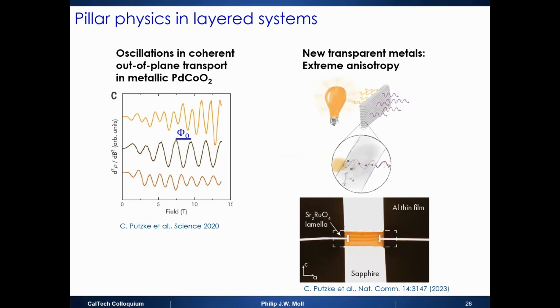These are layered materials. They like to go in the AB plane. Everybody knows how graphite looks. It's that black and shiny. And they like to grow in these big plates. But if you somehow take a slice, like you cut a slice through this, so you make an AC plane, you have a very interesting structure, because now this is highly conductive in the sheets, but is highly insulating, or at least very poorly conductive in the perpendicular direction.